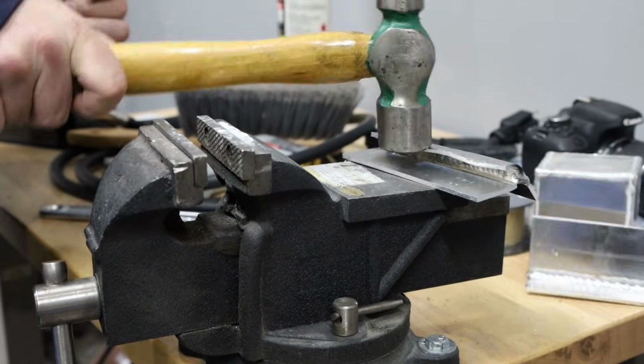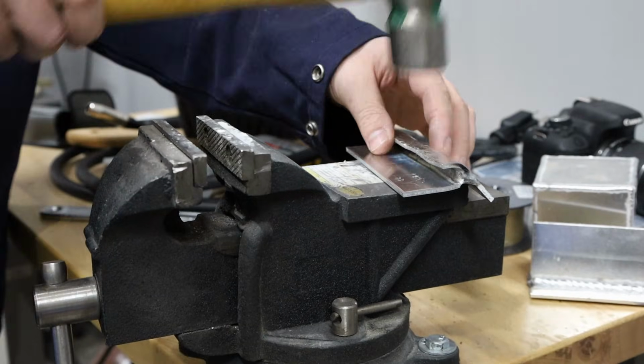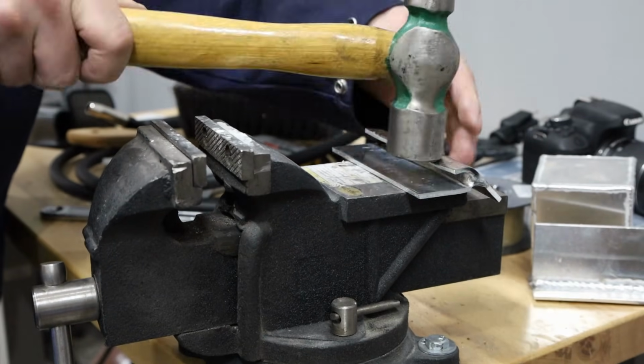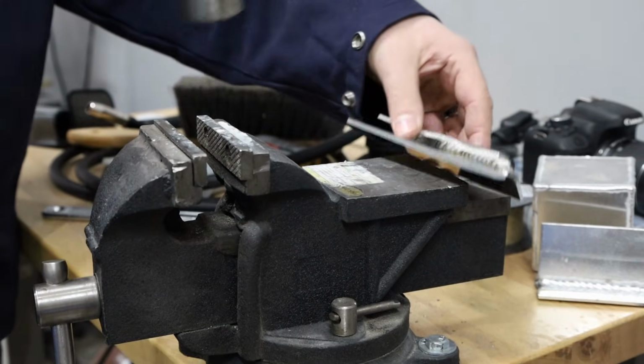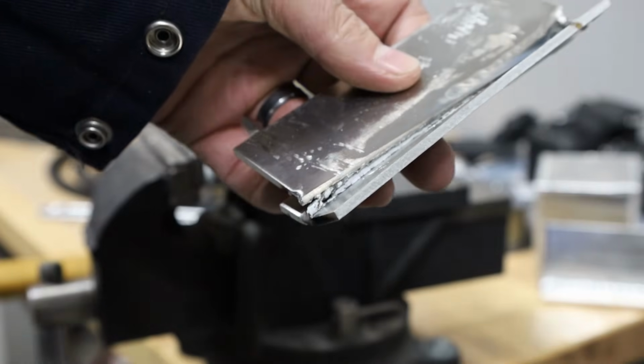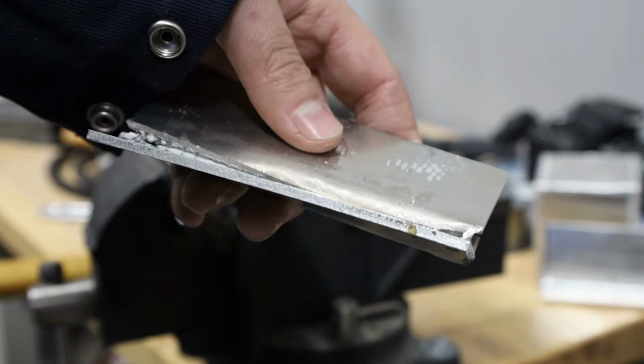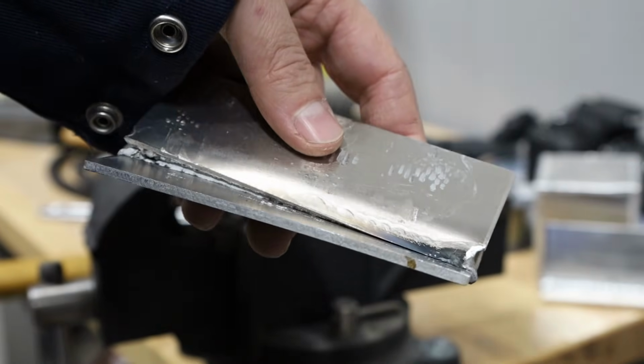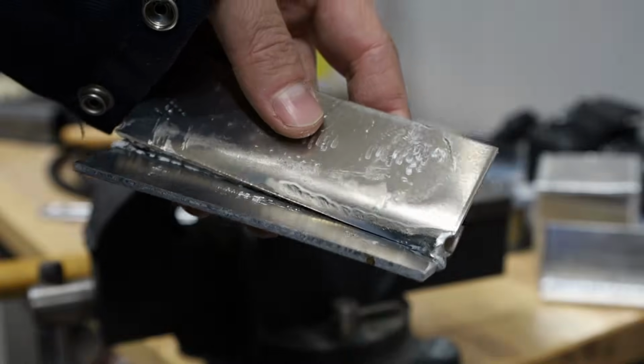I'm bending this open here just to see how it's holding up. And we'll take a look at what happened. So you can see that first half where it just ripped right open, and the second half is welded solid. So you can see it wasn't fused very well on the bottom there in the first half. And so I know that I needed to correct that with my technique.